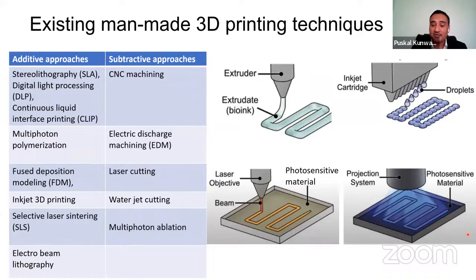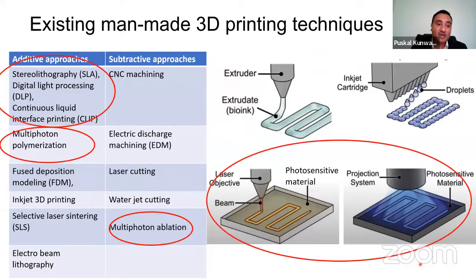Widely used, another is optical projection lithography. So basically here, rather than scanning, like in laser writing, you create a pattern of light, and that pattern is projected onto your photosensitive material, and you can print a single layer. Now, iteration of these layers can result in a 3D structure. So we are mostly interested in these two, optical projection lithography as well as direct laser writing.